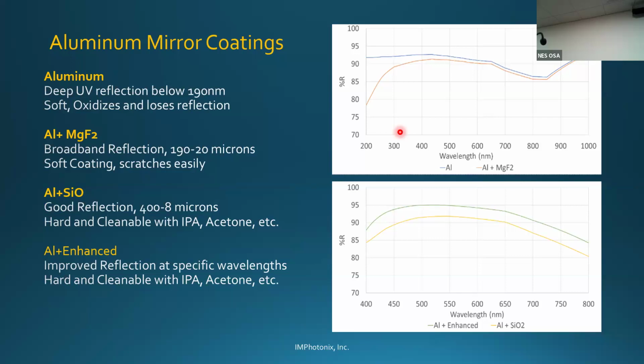So here is a little bit more technical information on these coatings. For basic aluminum mirror coatings, that coating has the broadest reflectance range. It does have some drawbacks. One, it's soft and it oxidizes easily unless you put a protective overcoat on it. But aluminum has good reflectivity, especially in the deep UV, as long as it's kept away from moisture, usually in a system that's purged with nitrogen. Again, we can protect it with a magnesium fluoride overcoat. You will lose reflection below 190 nanometers because of the absorption of the magnesium fluoride, but it still retains most of its reflectance over a very broad band in the UV.